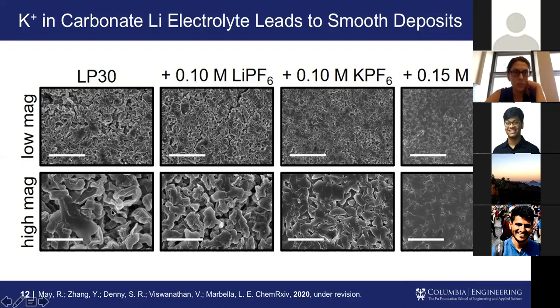So you can see that whenever we do this experiment, we get these high surface area structures. Some of them look very pointy. If we continued to grow, maybe they would grow and pierce the separator. So it doesn't look like a very good scenario here, which is consistent with what we know. If you push conventional carbonate electrolytes too hard, then you end up getting these sharp dendritic growths. So what we tried to do was see, could we add in some, say, potassium ions in very, very small concentrations and improve this deposition morphology. What we see is that if we add in a little bit of potassium, 0.1 molar potassium to a 1 molar lithium electrolyte, it starts to get a little bit smoother.